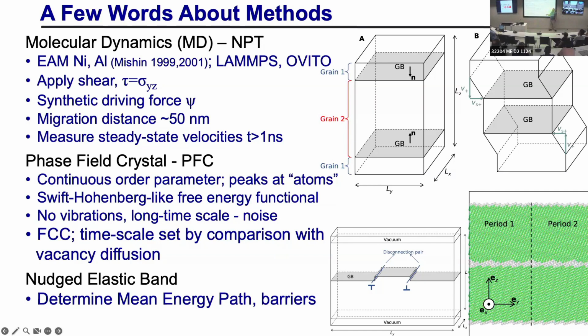It turns out in bicrystals, unlike free surfaces, those steps have Burgers vectors or dislocation character associated with them. And that's why you get this shear coupling: the steps, when they move, translate the boundary, but they also move the Burgers vectors, and that gives you the shear. That's why the two things are coupled. So that's basically a unit cell for nucleation of a disconnection pair and propagation. This will set the barriers for the motion.